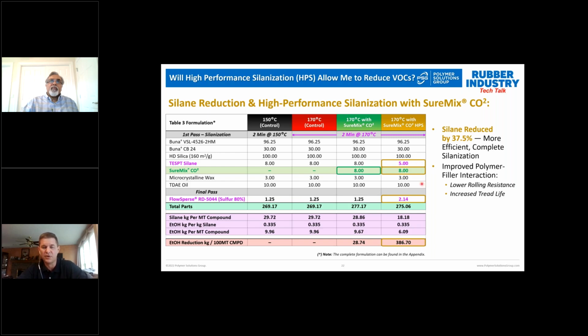So one thing that you'll also notice is the sulfur loading. Whenever you change your silane in a sulfur cured compound, it's important to adjust the total sulfur in the compound so you can maintain the modulus, because by taking out silane, we're taking out the donating sulfur from that silane.